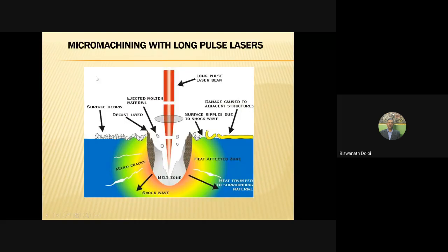Now here you see, this is the machining with a long pulse laser. The laser pulse duration is long, millisecond or microsecond. Then there is melting, so a lot of thermal related problems are there: micro cracks, heat affected zone, damage to the adjacent layer, recast layer, resolidified layer. So this is not desirable.